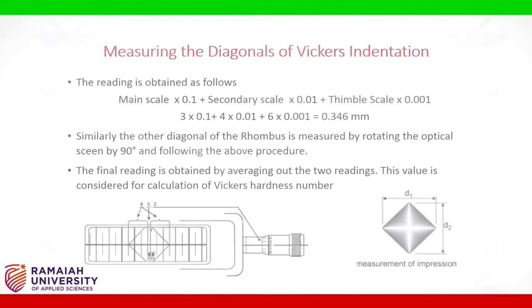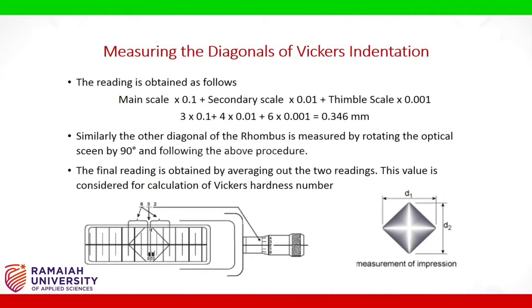The reading is obtained by adding the readings from the initial scale, the secondary scale, and the thimble scale. For example, initial scale reading 3 multiplied by 0.1 is added to the secondary scale of 4 multiplied by 0.01, and this is added to the thimble scale of 6, which is multiplied by 0.001. The reading will now be 0.346 mm.